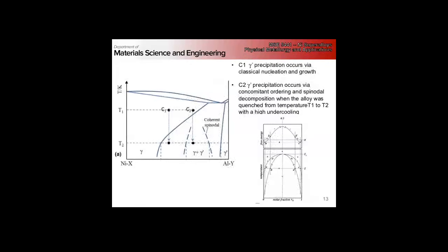And just as a reminder, spinodal, right, where we spontaneously come down and we separate into two phases. Points B and D are the spinodal points, and that's the composition that we will spontaneously separate to. It's not the lowest energy configuration - we can't actually get to the bottom of the well. We need long-range diffusion for that.